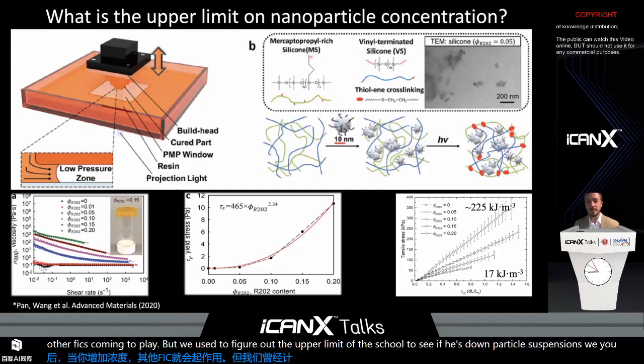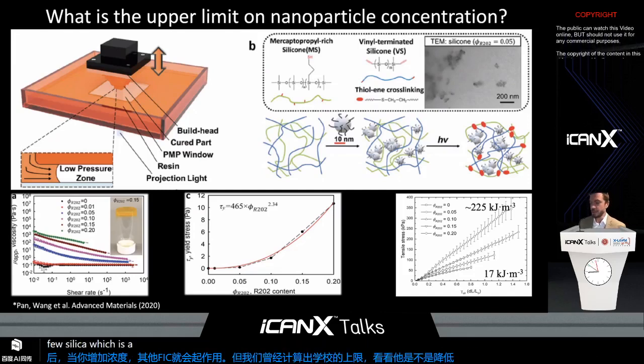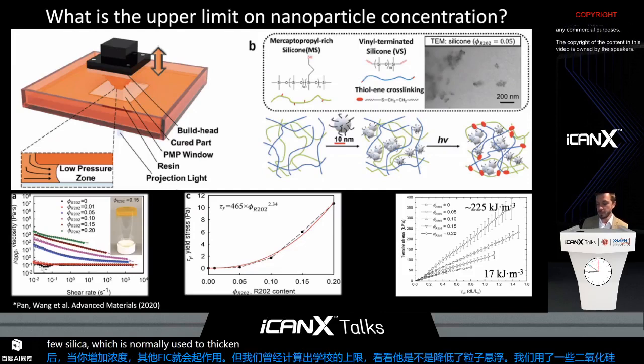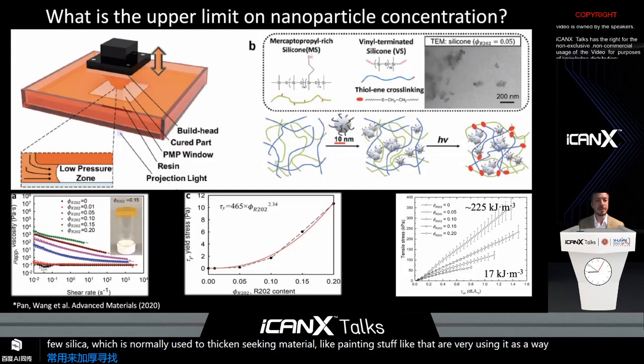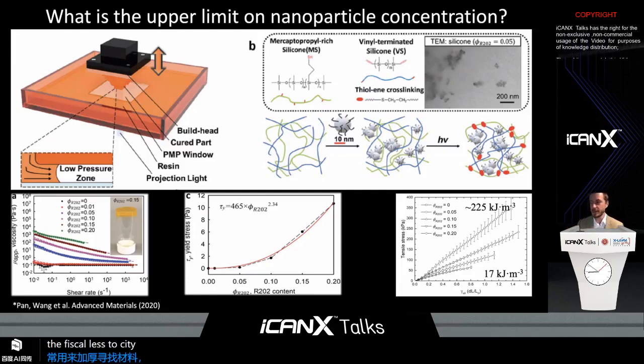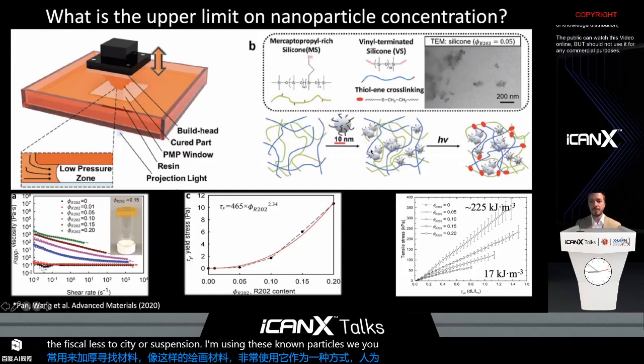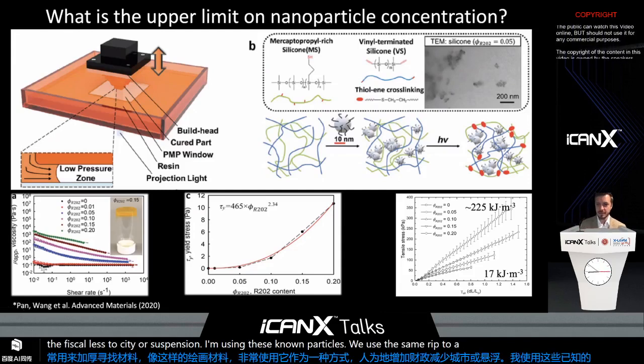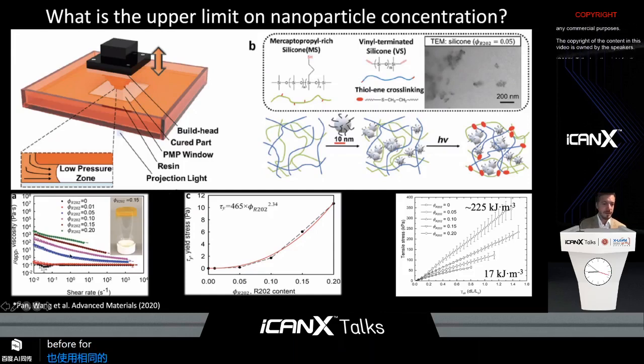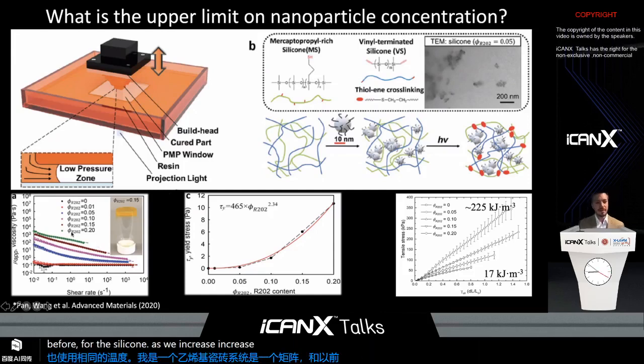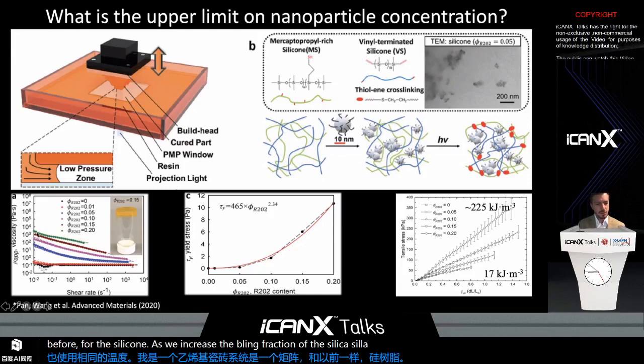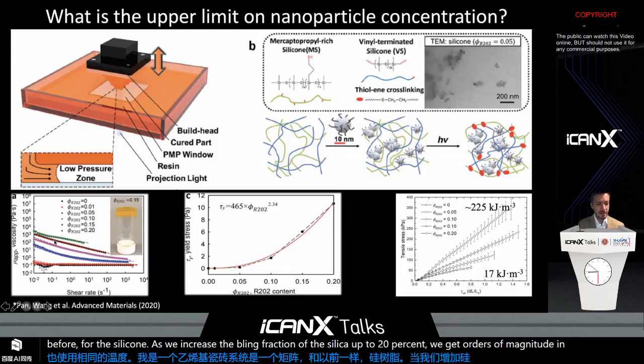We used a fumed silica, which is normally used to thicken material like paint and stuff like that. But we were using it as a way to artificially increase the viscoelasticity of our suspension using these nanoparticles. We used that same mercapto vinyl thiol-ene system as matrix as before for the silicone. And as we increase the volume fraction of the silica up to 20%, we get orders of magnitude increase in the apparent viscosity.